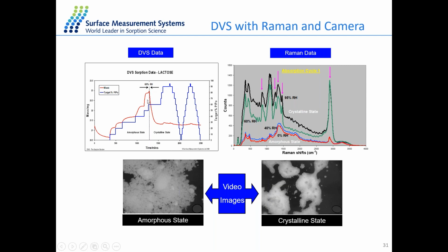You see at the 60% RH step, the sample mass change decreases dramatically, which is because the sample is changing structure from the amorphous to the crystalline state. It has a significant change because the crystalline state has a smaller surface area and less sorption capacity. This information is detected by the Raman spectra that we take at the end of each relative humidity stage. At 0 to 40% RH, the spectra show very broad features, as for the amorphous state. After 60% RH, some different peaks and different intensities appear in the Raman spectra, which is due to the crystalline change, the phase change of the sample.